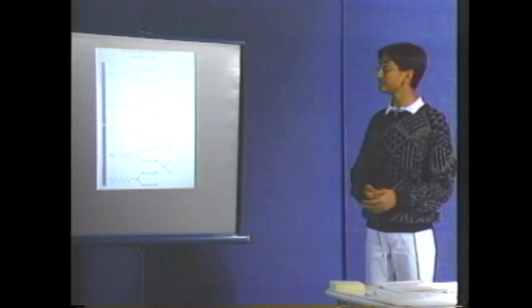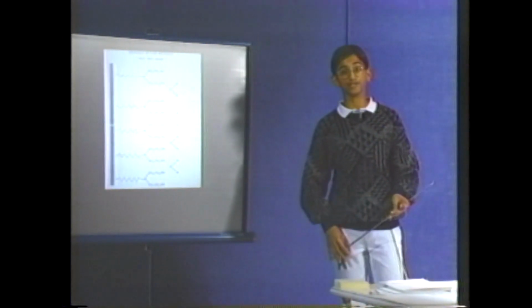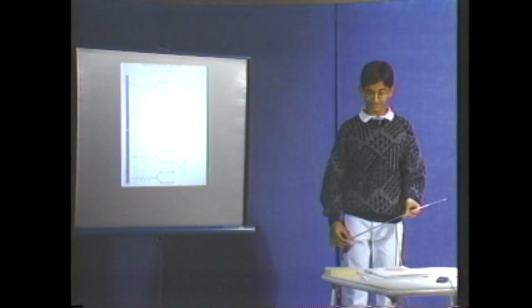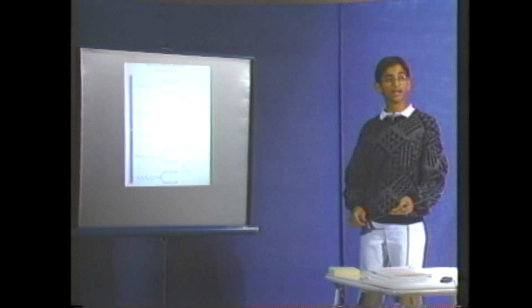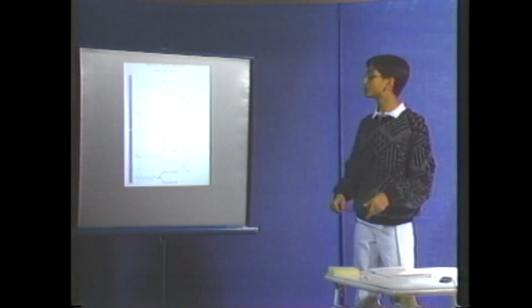In the case of plexiglass, however, no known record is available in the literature on the effectiveness of surfactants as topical antistats. One more thing about the surfactants, and this is that the treatments that the surfactants bring about are fugitive and can be readily washed away with water. The antistatic effect on the substrate is thus lost with time.